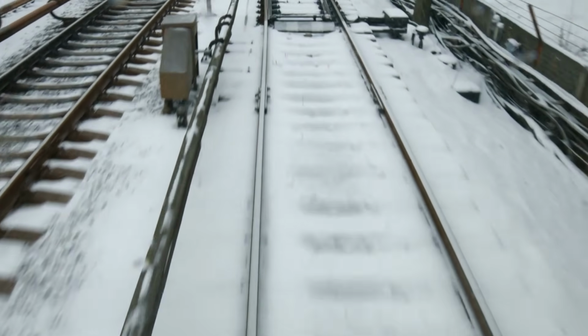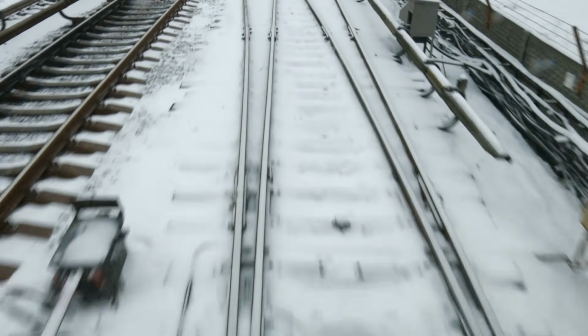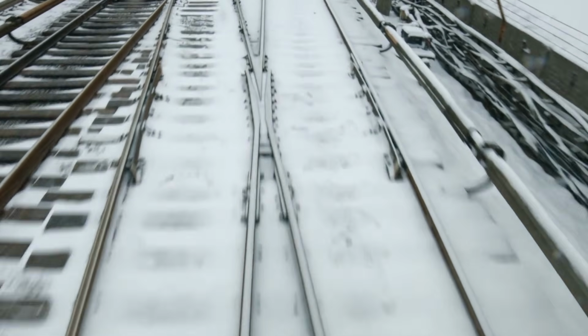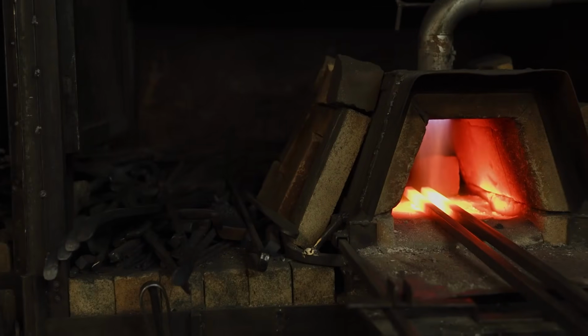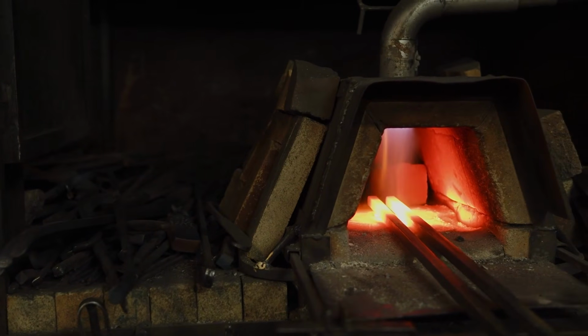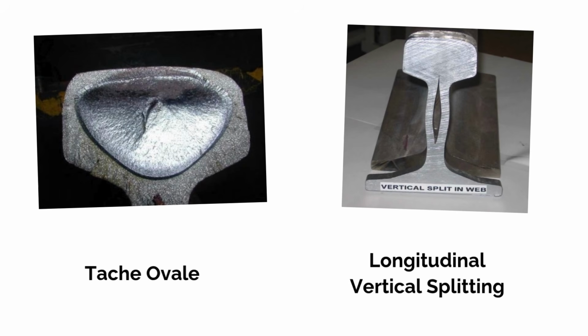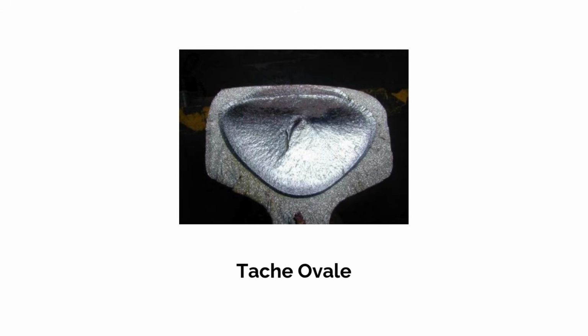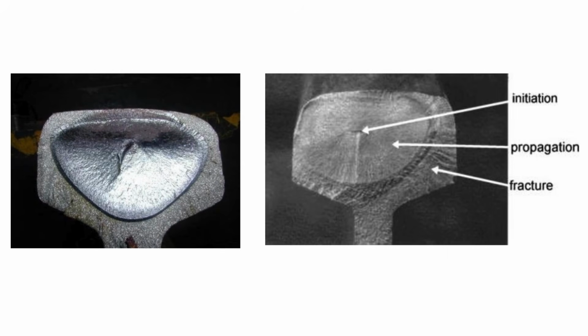Internal defects is a name given to flaws, inclusions, or weaknesses within the steel material of the rail itself. Often these defects are present or created when the rail itself is initially manufactured. Two examples of internal defects are tache ovales and longitudinal vertical splitting, or LVS for short. Tache ovale means oval spot in French, which is the perfect description of what the defect looks like. Often shortened to TO, a tache ovale is a fatigue crack in the rail head, caused by excessive hydrogen in the metal of the rail during or soon after production.